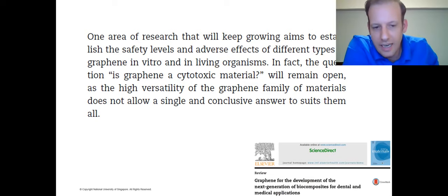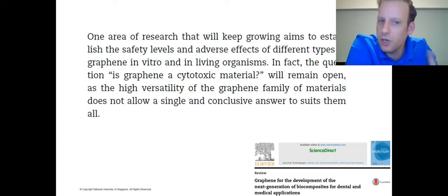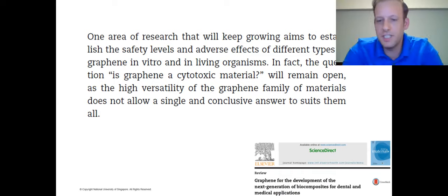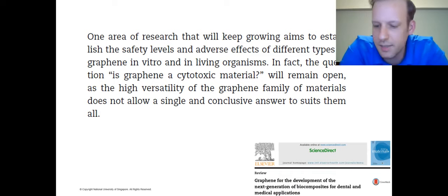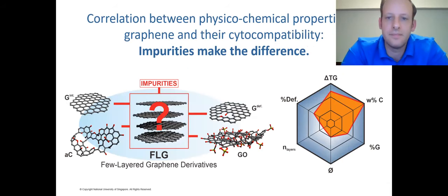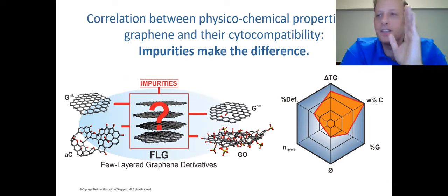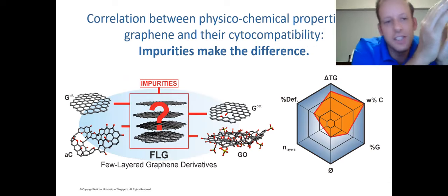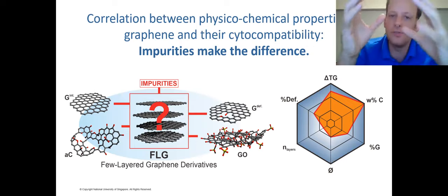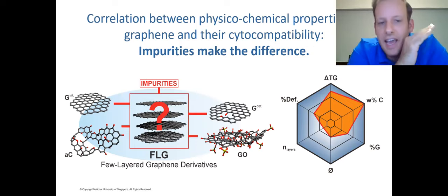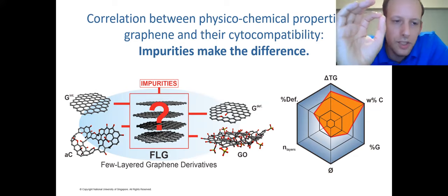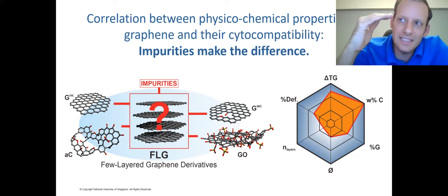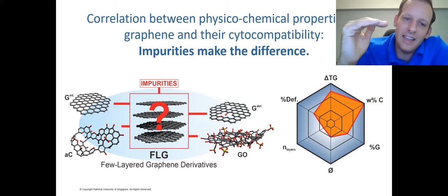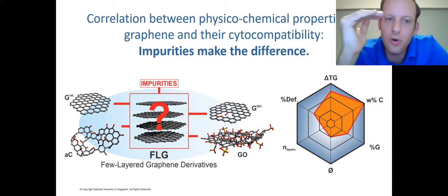We have actually done a very comprehensive study on the toxicity of graphene materials that we expect to see published in the next few months. We have just submitted the paper in which we evaluated the properties of more than 40 types of graphene. Not only the physical properties, but their chemical properties and also their cytocompatibility. And in the end of this study, we concluded several things, but the aspect that deserves to be highlighted is that what changes the cytocompatible character of graphene a lot is its quality.